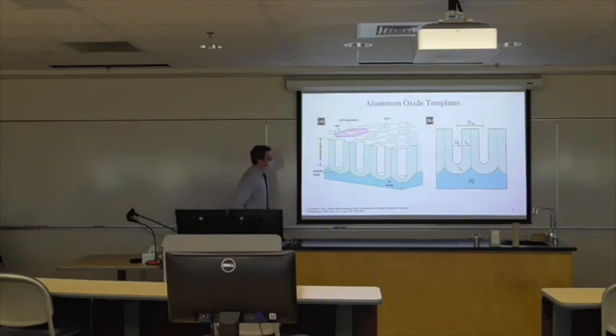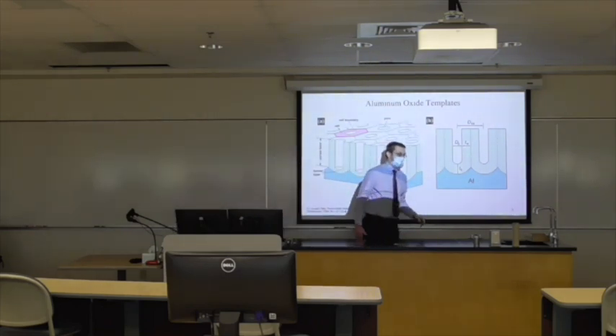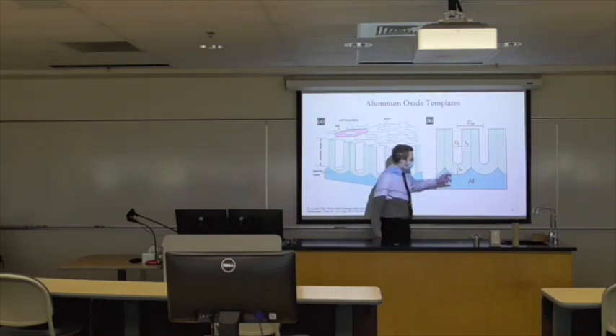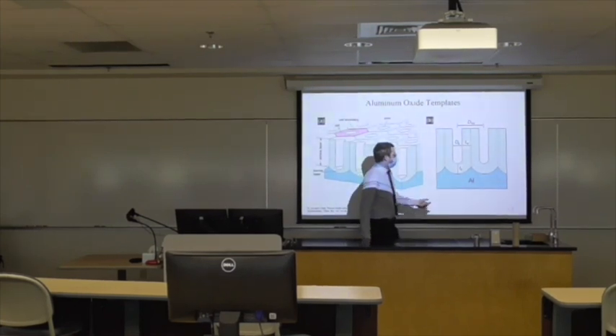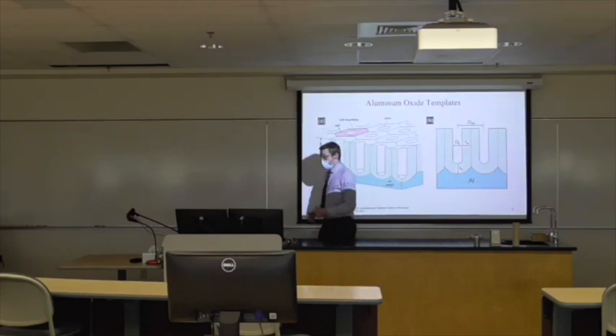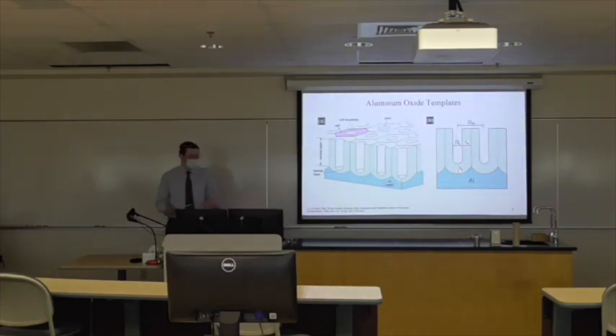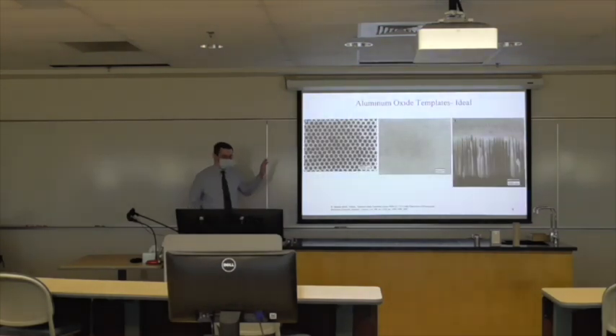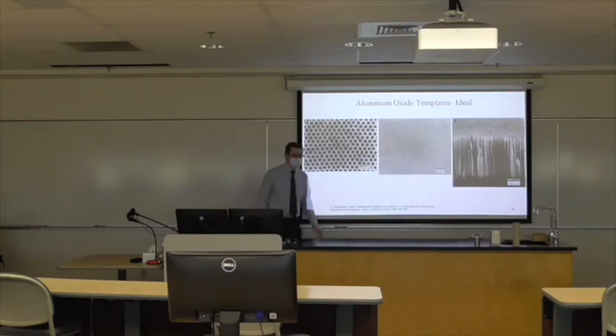It was shown by O'Sullivan and Wood a long time ago that the thickness of the barrier layer between the aluminum and the actual air, as well as the pore diameter, are both dependent upon the voltage applied. So we can use these to make the aluminum oxide templates. Now, that was arguably still sort of theoretical up until the paper by Masuda and Fukuda in Science, where they were able to produce these idealized aluminum oxide templates.